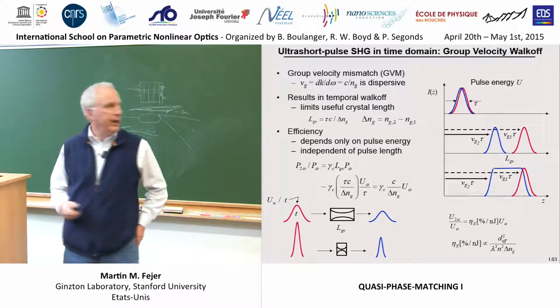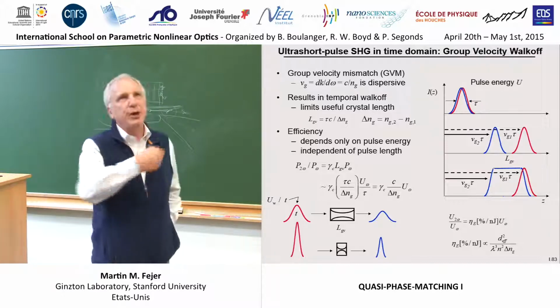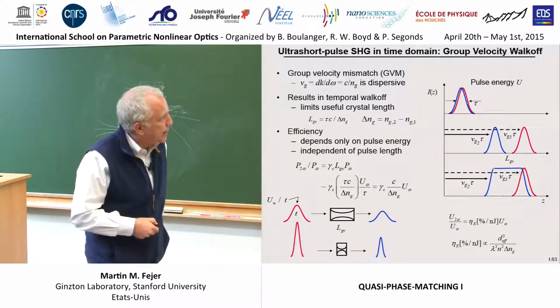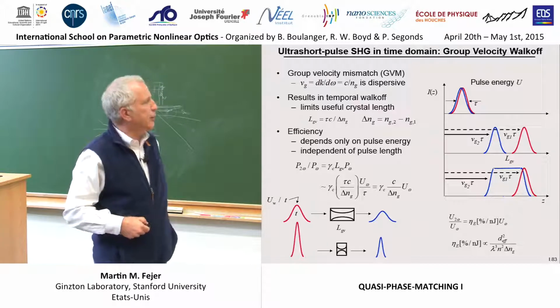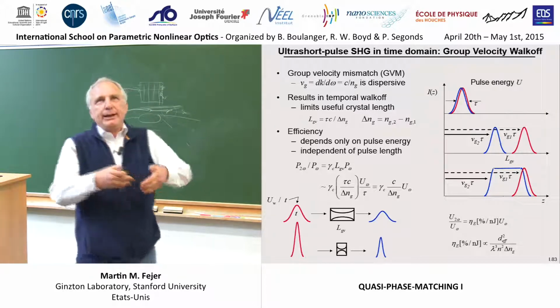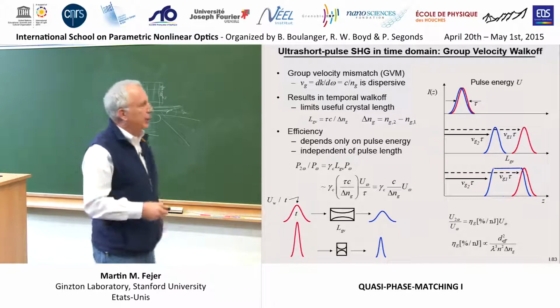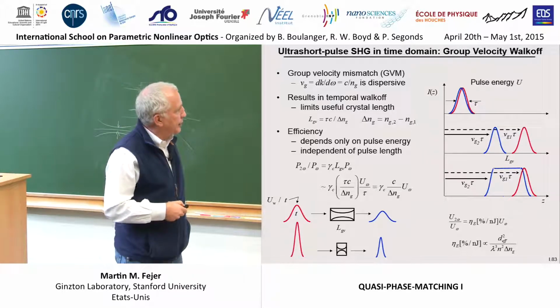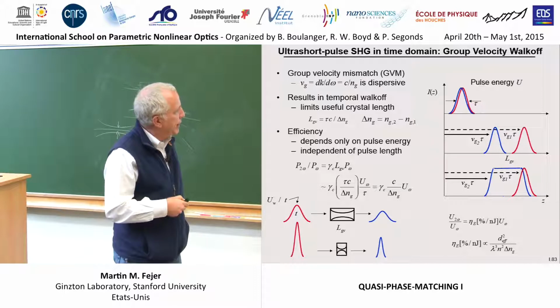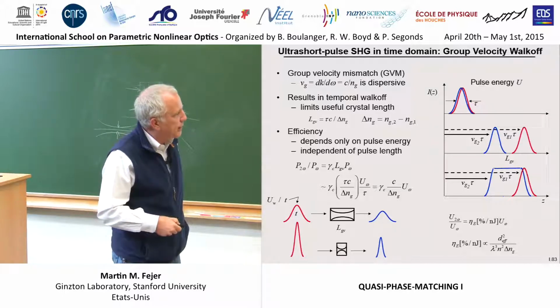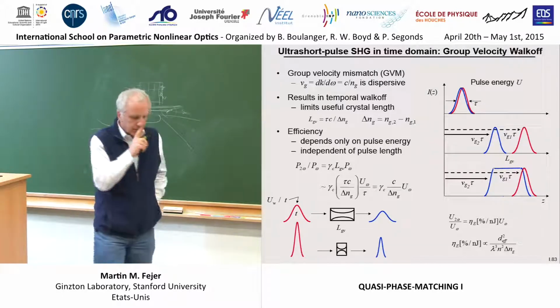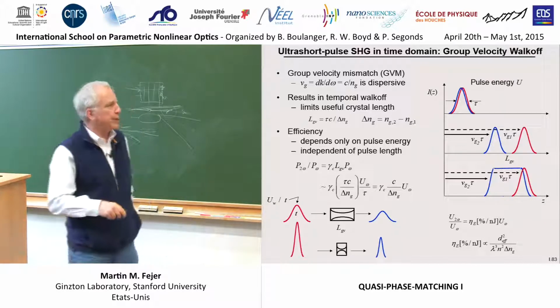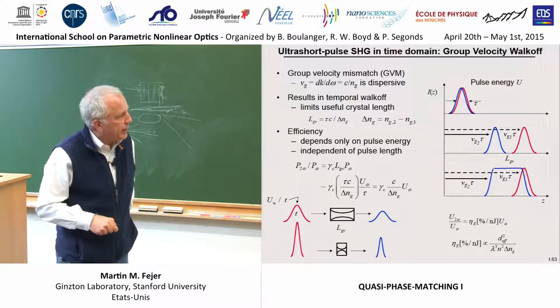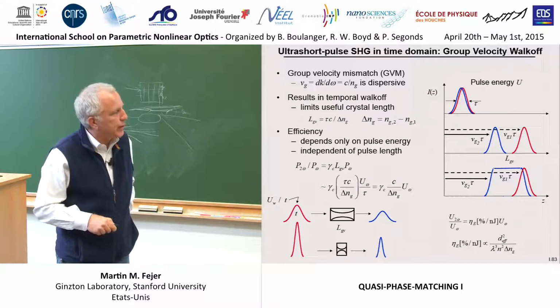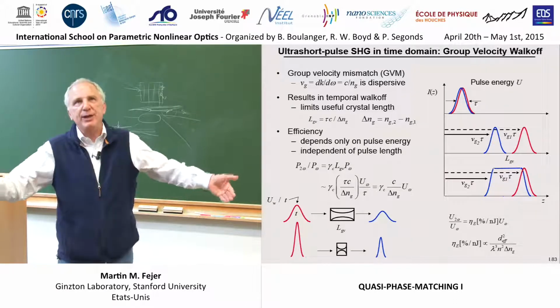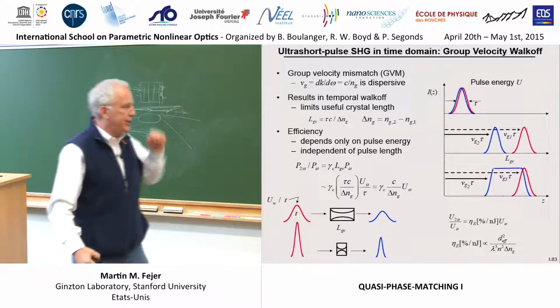And so you can come up with a figure of merit for this ultrafast kind of harmonic generation, which has units of percent per nanojoule, which is a material property that depends on the square of the nonlinear coefficient. That goes into this ordinary mixing efficiency and goes inversely with the group velocity mismatch. So you might think that quasi-phase matched crystals would be lousy for this job because they're not even phase velocity matched, much less group velocity matched.